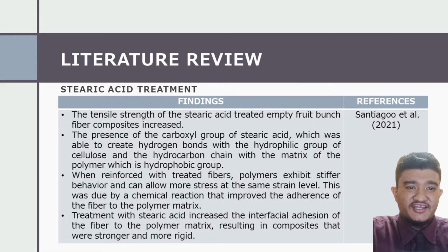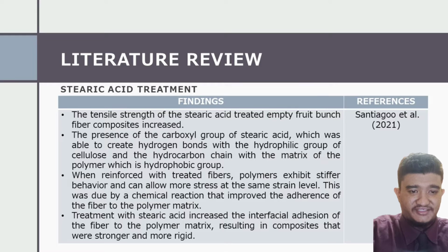From the finding on stearic acid treatment, the tensile strength of the stearic acid treated empty fruit bunch fiber composite was increased. The carboxylic group of stearic acid is able to create hydrogen bonds with the hydrophilic group of the cellulose, and the hydrocarbon chain with the matrix of the polymer, which is a hydrophobic group. When reinforced with treated fiber, the polymer exhibits stiffer behavior and can allow more stress at the same strain level. This was due to a chemical reaction that improved the adherence of the fiber to the polymer matrix.